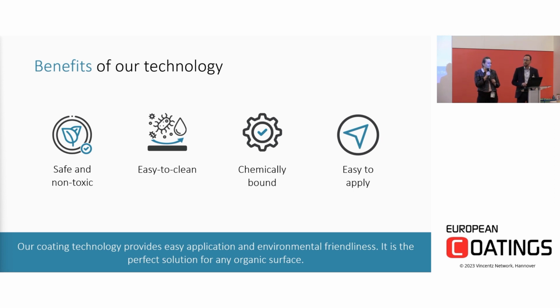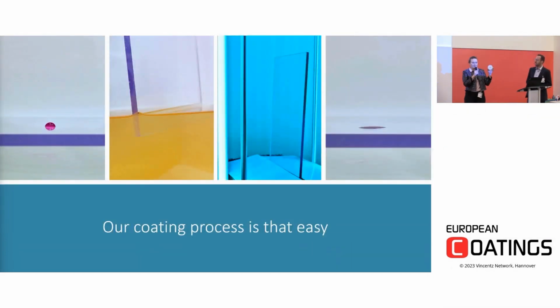Another advantage is it's very, very easy to apply to the surface. So this is our product. It's a solid polymer, a powder, and you can just dissolve it in water or in alcohol or in mixtures thereof, and then you can use either spray coating or dip coating to apply it to your surface. Then you switch on the UV lamp for 20-30 seconds, and our polymer can then react with the surface. The only limitation here is that you need a CH bond. Our polymer reacts with any CH bond on the surface. So we can functionalize any plastic, from PP, PEEK to ABS, PU, but what we can't do is any inorganic. So glass, metal, that is out of our scope.